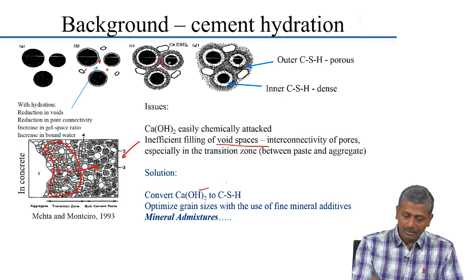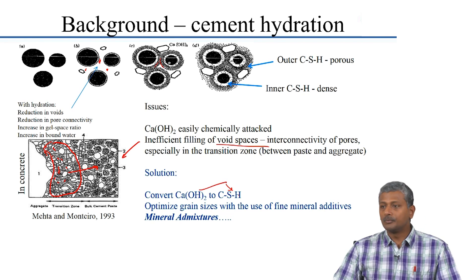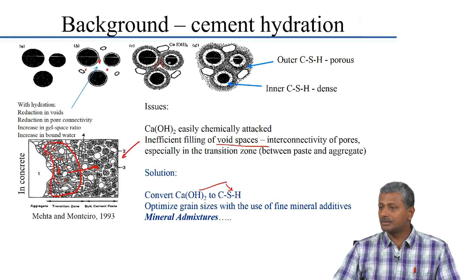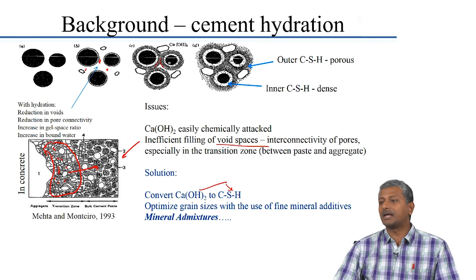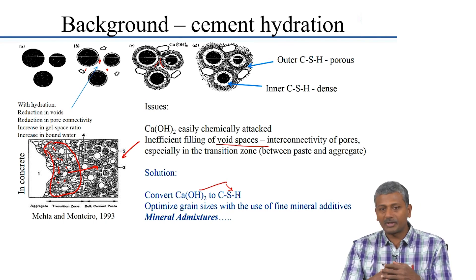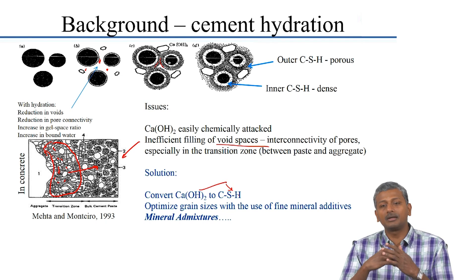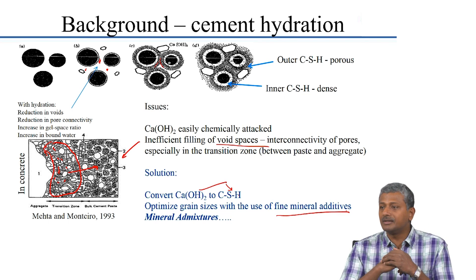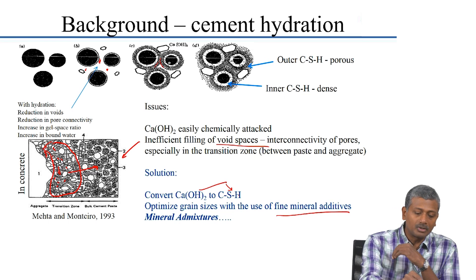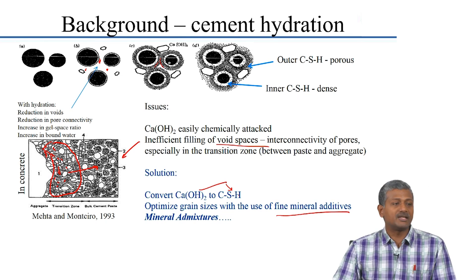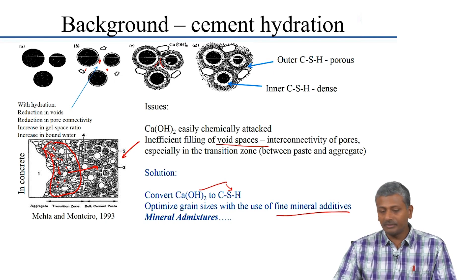The solution is to convert calcium hydroxide to useful calcium silicate hydrate, which is a semi-crystalline material. It occupies a very large volume because of its good space-filling ability thanks to its large surface area, as opposed to calcium hydroxide. This fills up more space, reducing porosity and blocking pores to reduce their interconnectivity. Fine mineral additives can also block pores especially in the ITZ, leading to a much more densified ITZ. The solution that tackles both these issues at once is the use of mineral admixtures or supplementary cementing materials.